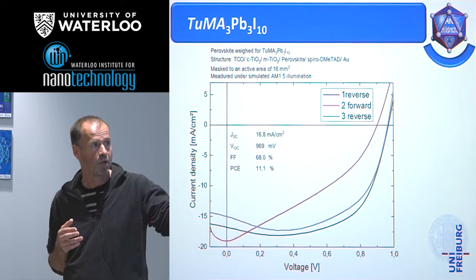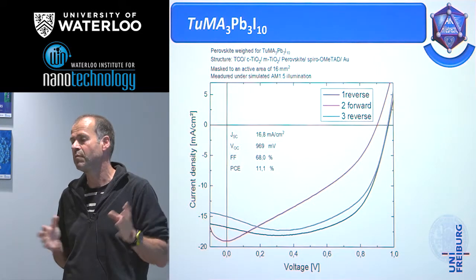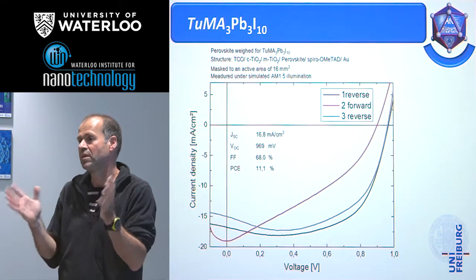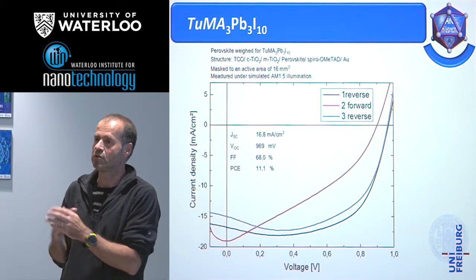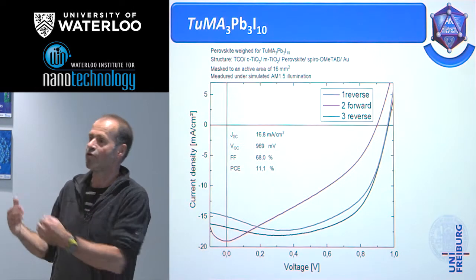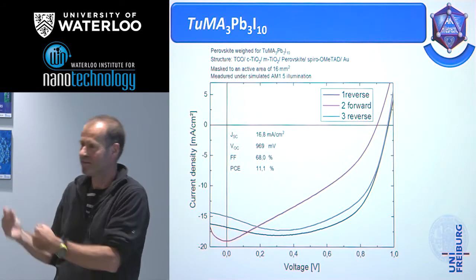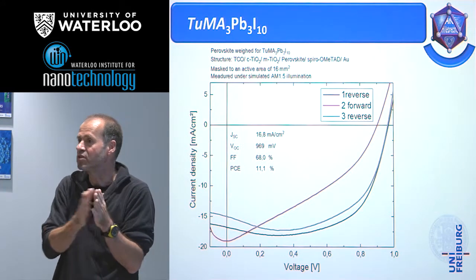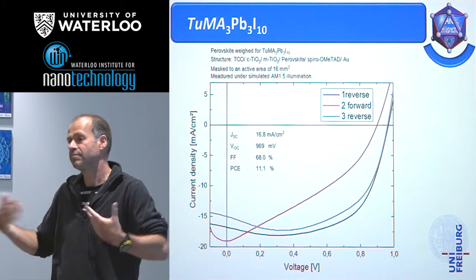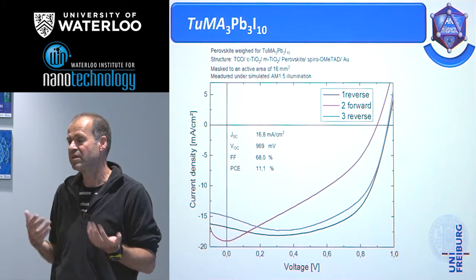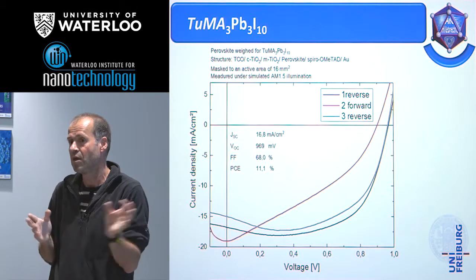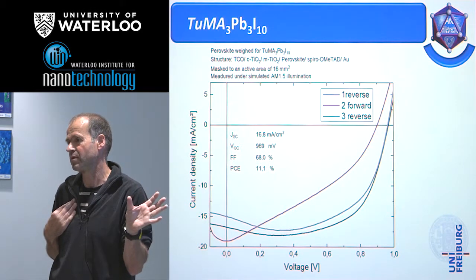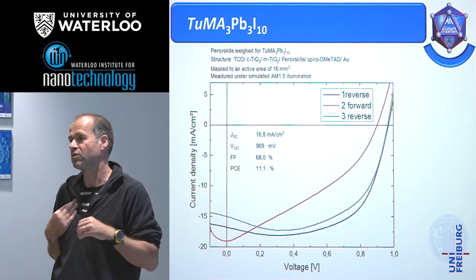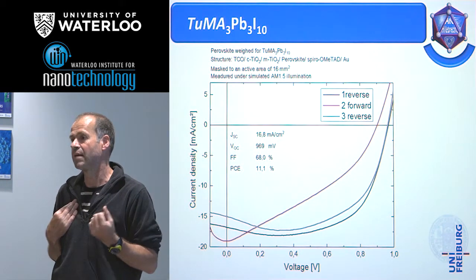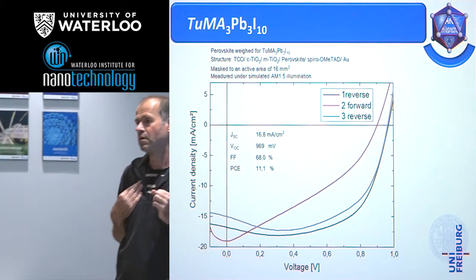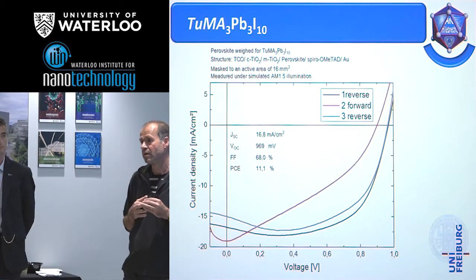For example, the substitution with cesium and formamidinium, we have a system containing 3 different cations, and it's very difficult to have a well-defined process for the precipitation of a well-defined layer if you know that the concentrations vary during the ongoing precipitation process. And it's very difficult to steer it if you have so many components. And I guess with 2 organic cations, it's possible. But with 3, or additionally with a variation of the halide, it's very difficult to get reliable results and long-term stabilities. We can probably discuss more at lunch about the long-term stability.